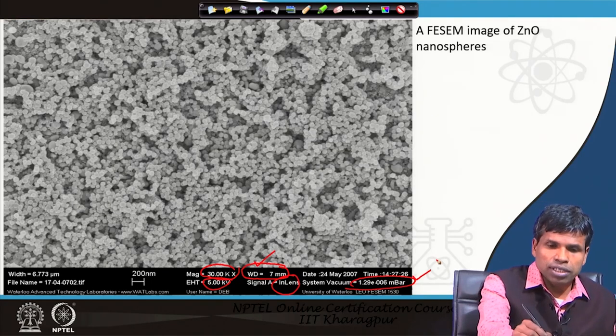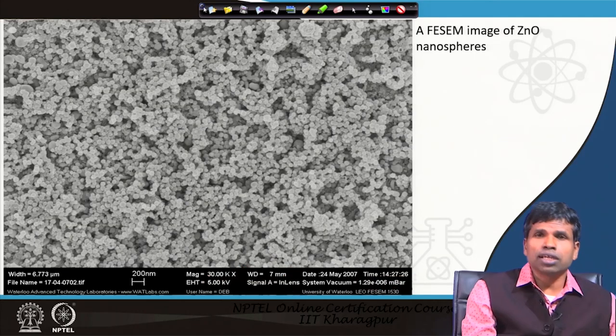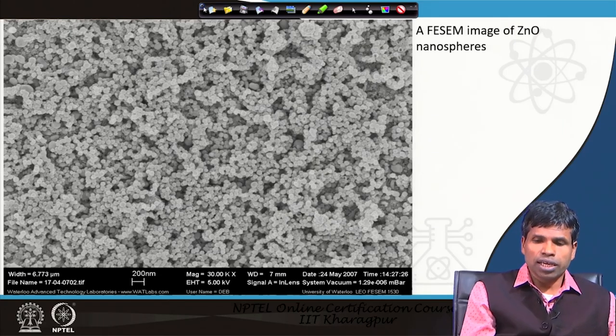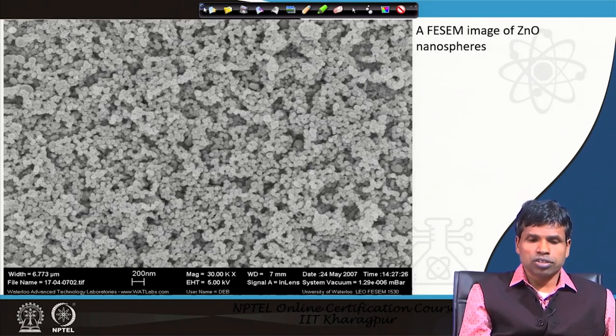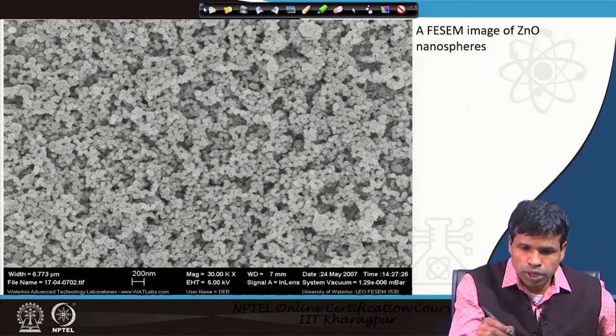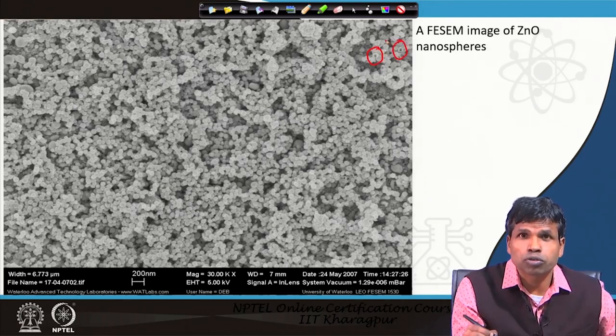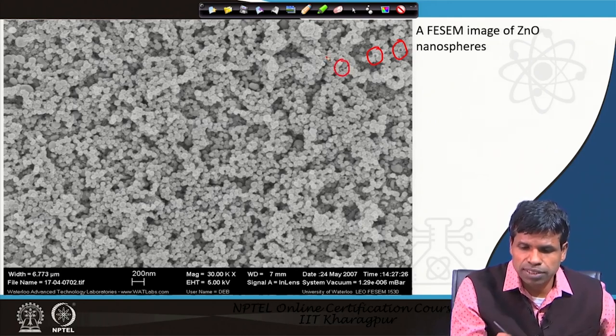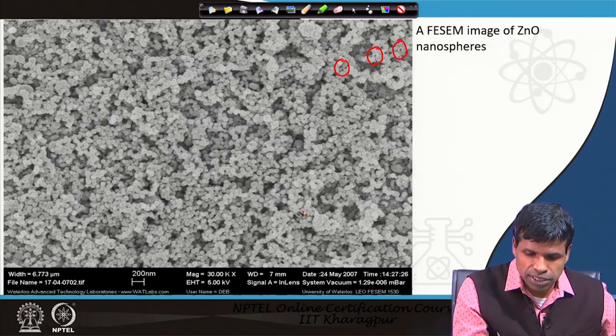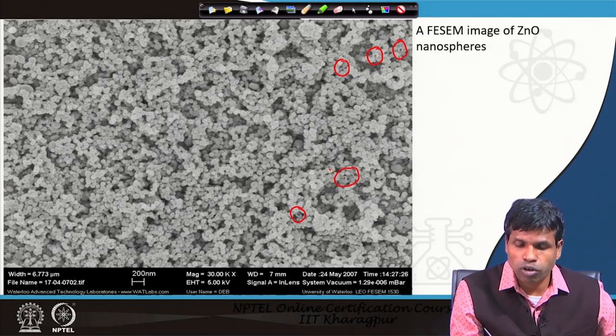These are the different pieces of information present on most SEM photographs. Most important is that you see a three-dimensional image and can know the size of objects on your sample. These are spherical structures, but if you look very carefully you can see some of these spheres are hollow in nature. From the broken spheres, we can tell they are hollow — the middle of such a sphere shows darker contrast or less brightness, indicating the hollow nature.